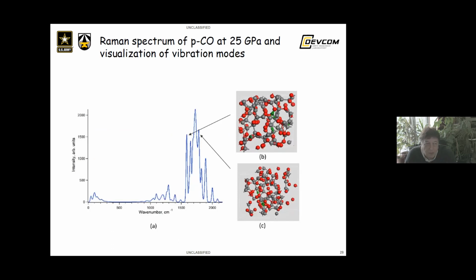The Raman spectrum of amorphous polyCO calculated using density functional perturbation theory is shown here, together with visualization of CC and CO stretching. Vibration modes corresponding to the peaks at 1600 and 1800 inverse centimeters are considered as the signatures of polyCO.